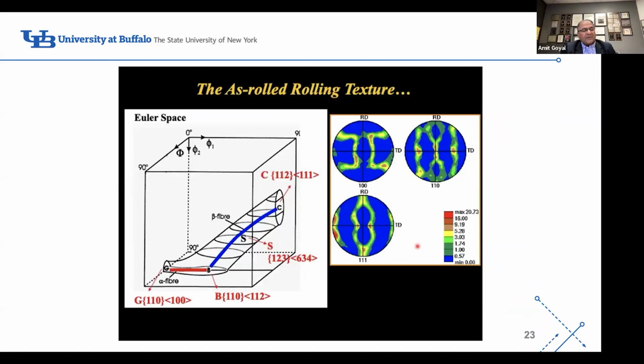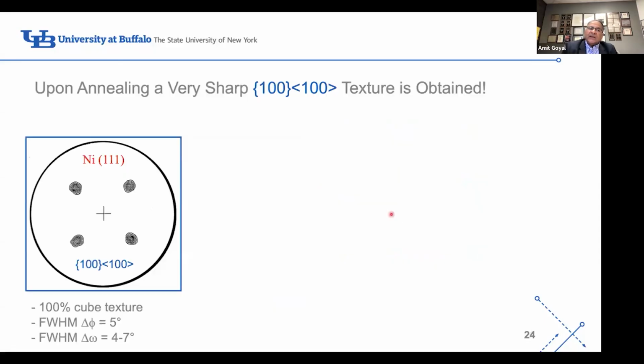So in the field of thermomechanical processing, which is an old field for over 100 years, it was not deemed possible, or it was not believed that one can create a thermomechanical texture which could be so sharp that we remove all high angle boundaries. So it was quite interesting for them to hear what we had done, where we worked with this Euler space. You're looking at the various orientations possible when you roll a piece of metal, an FCC metal, and the two-dimensional pole figures. But we get, after annealing, a near perfect cube texture.